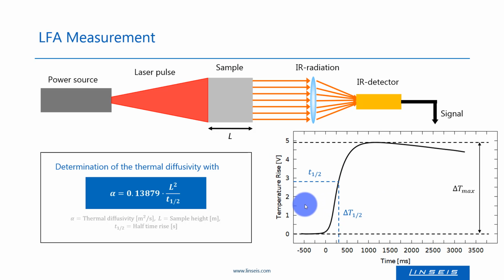For the calculation of the thermal diffusivity, one needs to determine the baseline and the maximum temperature rise, determine the half-time required from the initiation of the heating pulse to reach half of the maximum temperature rise. This time is called T1 half or half-time rise. With this knowledge, we can calculate the thermal diffusivity according to this very simple formula, where alpha is the thermal diffusivity, L is the thickness of the sample, and the half-time rise is T1 half.